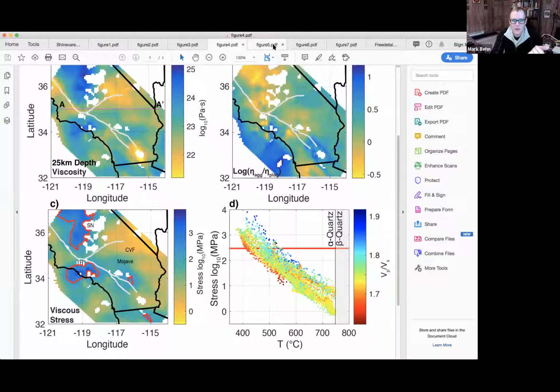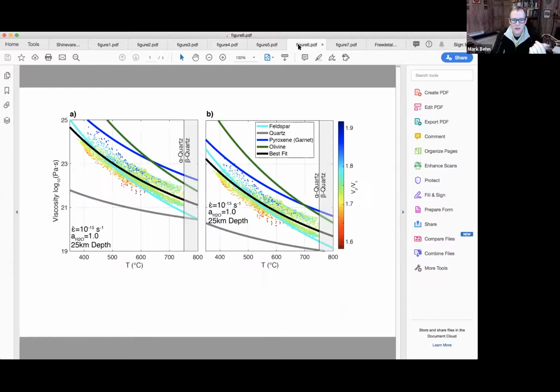And so what's interesting is if you look at all of the data points from his crustal structure at different temperatures and compare those to different single phase flow laws, the dots are individual data points where he's estimated viscosity, plotted on the y-axis, versus temperature from his temperature model. They're color-coded by that VP-VS ratio. And the best fitting flow law would be this black flow law here. And it is actually very close to feldspar for the lower crust.